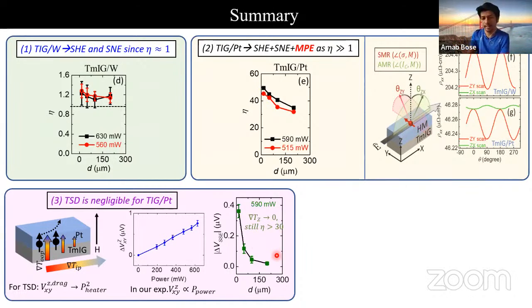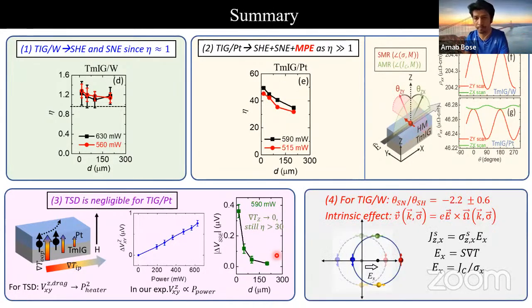is close to 0. And in the last, we can quantify an important parameter by taking the ratio of spin Hall and spin Nernst angle. This implies that if this ratio is equal to 1, there could be a universal electric field that will generate the transverse spin current, and it should not matter how that electric field is created, whether by applying electric current or by thermal gradient. So we analyze the data for TMIG tungsten because this system is quite clean, free from magnetic proximity effect in the temperature regime we worked. We find that the value is very close to 1 within our experimental uncertainty, suggesting a strong intrinsic contribution from the spin Berry curvature of tungsten.